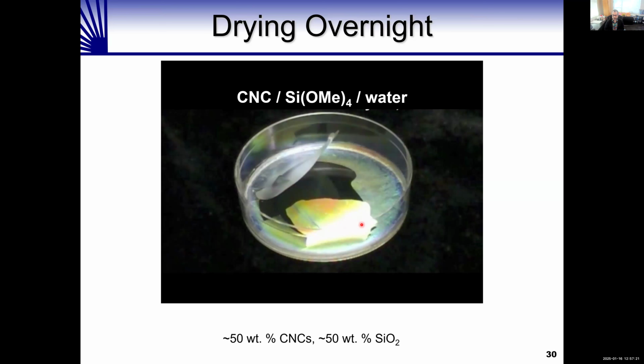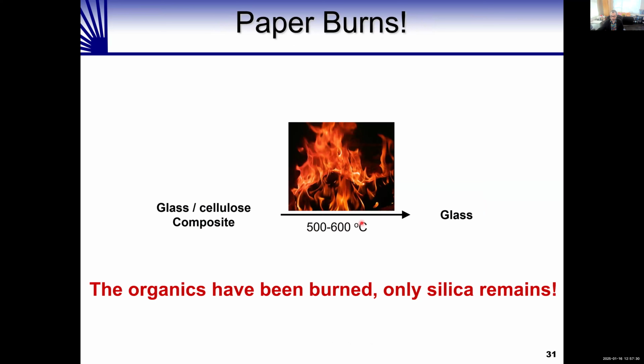So we've got a mixture of cellulose and silica. What do we do next? Well, we take this film and we burn it. We cook it at 500 to 600 degrees Celsius under air. That destroys all the cellulose, converts it into water and CO2, and leaves us with pure silica, pure glass. So the materials I'm going to tell you about now are just made of silica—all the organic, all the cellulose nanocrystals, have been removed.